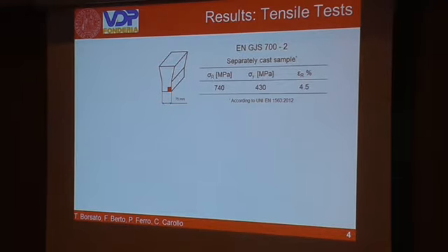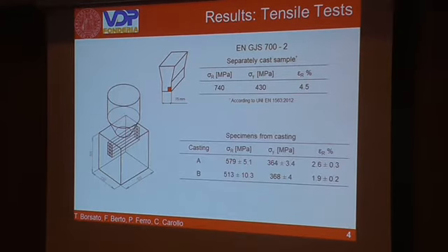In order to evaluate the mechanical properties of the material, a cast sample was cast according to the European standard, and specimens for the tensile tests were taken from the red zone in the figure. It can be noted that the results of the tensile test meet the requirements of a perlitic ductile iron.